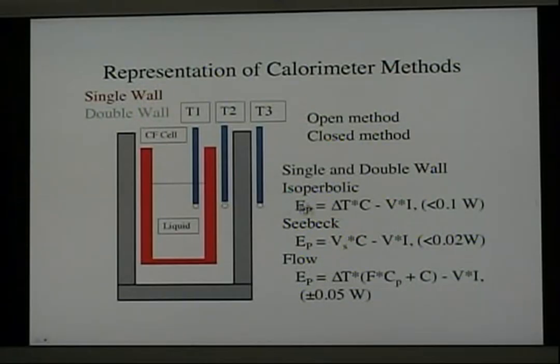Well, the methods for calculating the heat from these various techniques is fairly simple. In the isoperibolic techniques, the temperature difference is multiplied by a constant, which is the calibration constant that needs to be determined by experiment. And it's determined, I might add, by either placing a resistor in the cell through which a current flows, and the amount of power that is being generated within that resistor is then used to calibrate, or a dead cathode, one that does not produce any excess energy, is used, and the calibration is done by applying electrolytic current.